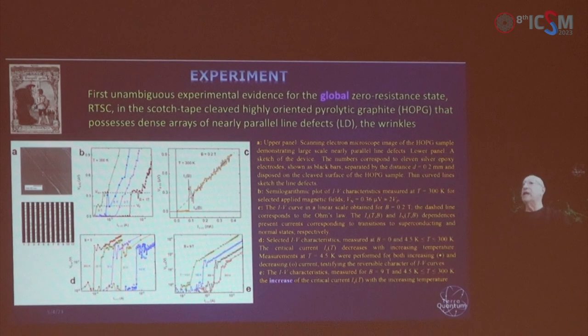So, first, again, we repeat our scanning electron microscope image of the graphite surface. This is the sketch of the experiment. And this is our data. These are semi-logarithmic IV plots, and measurements are taken at room temperature, and we clearly see the superconducting transition. And what we see is that the critical current for this superconducting transition